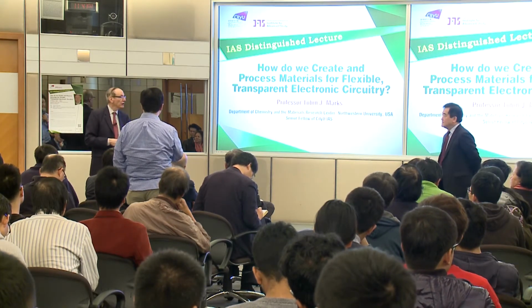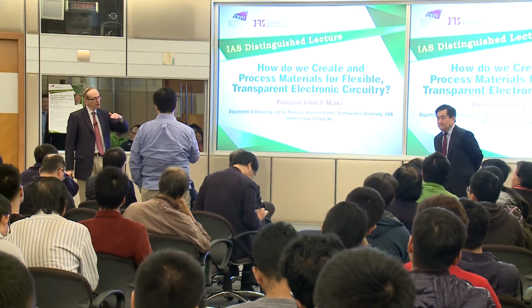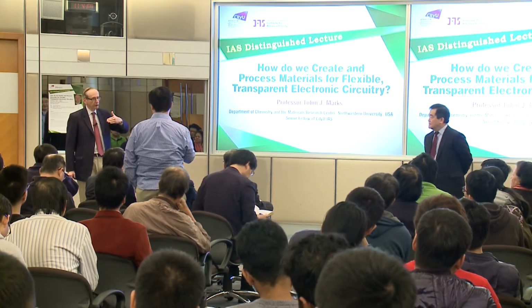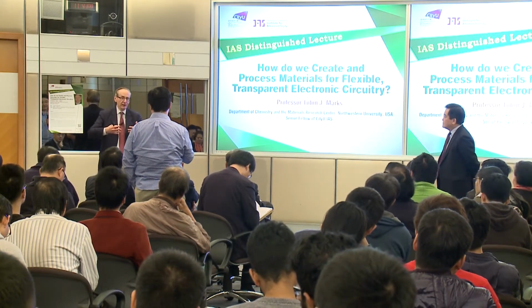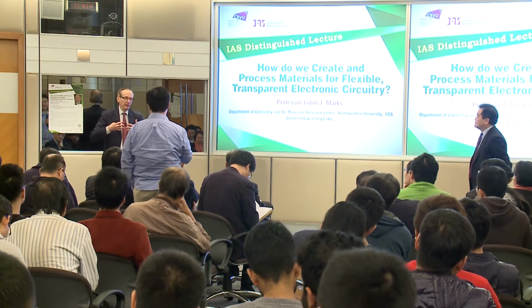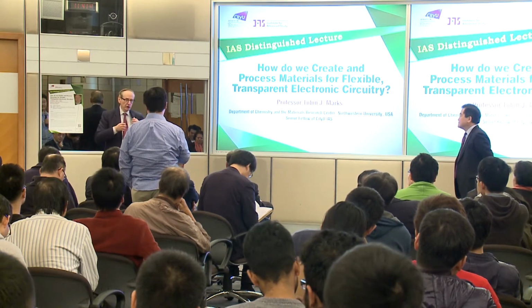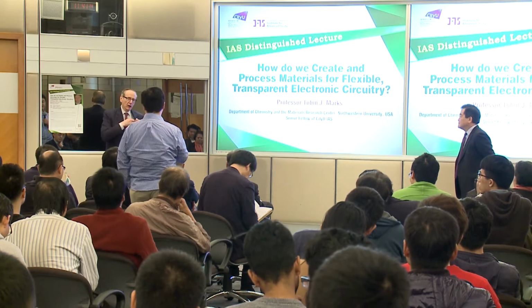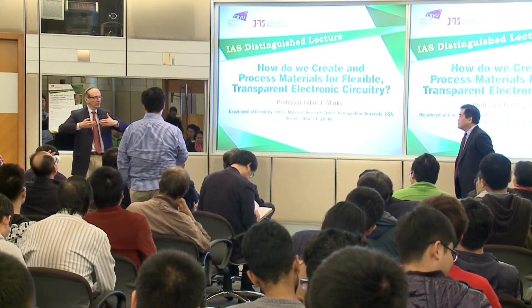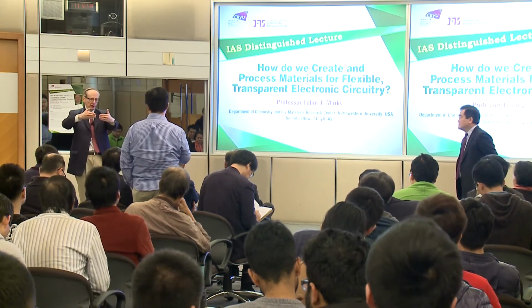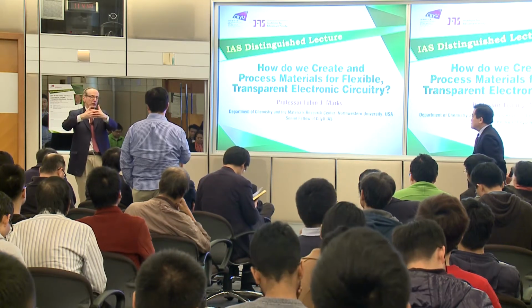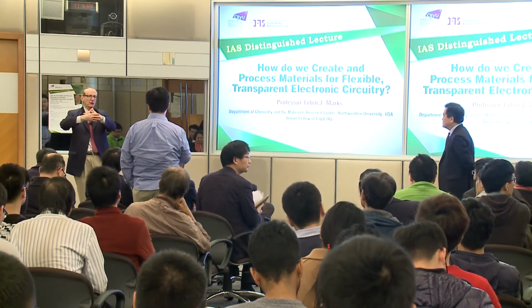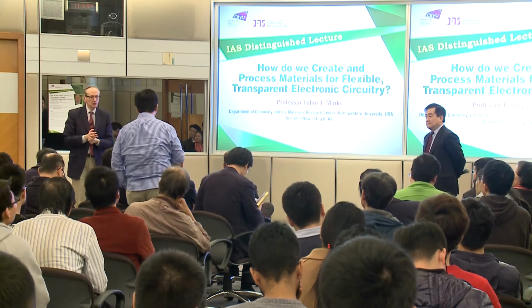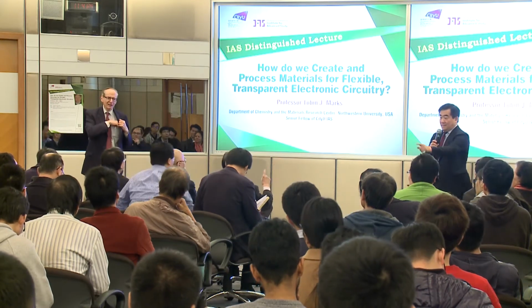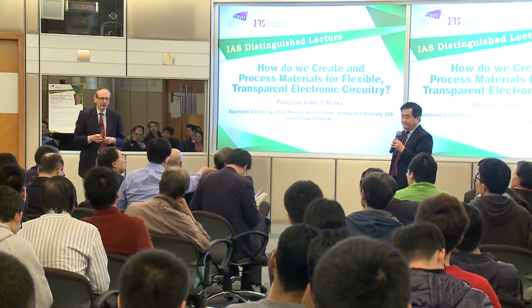It's a concern with IGZO too. If you have it in a light-emitting device, it's being irradiated, and that affects the threshold voltage of the IGZO. So what the manufacturers always do is put a little screen between the light source and the IGZO. Oh, that's great. And that's not so well understood, but it's probably different defects.